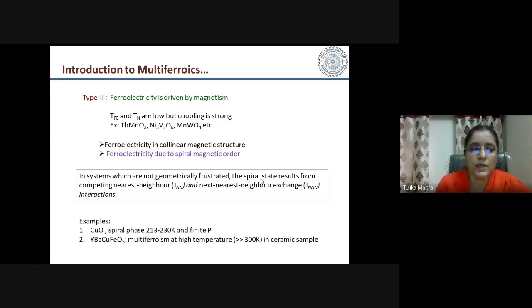So for this class of compounds where ferroelectricity is driven by spiral magnetic order, there are not many such compounds. One example is cupric oxide, where the spiral state is present between 213 Kelvin and 230 Kelvin. But this temperature window where the spiral state is seen is very narrow. Here both the spiral magnetic order and the electric polarization are finite and the orders coexist in this range, but the window is very narrow.